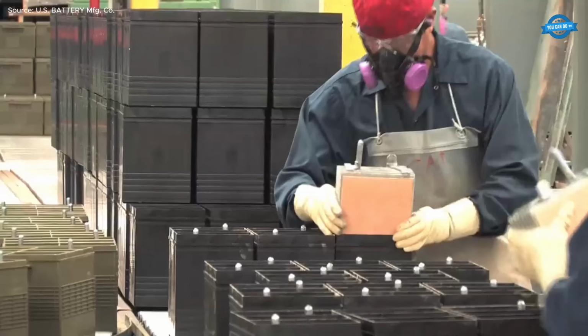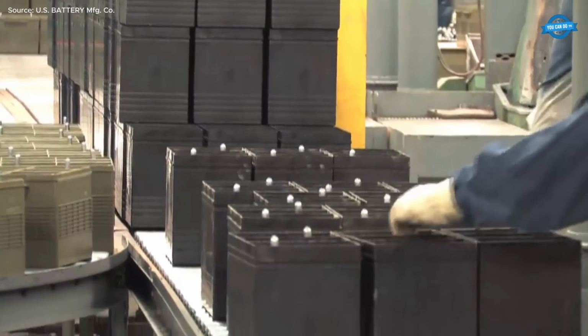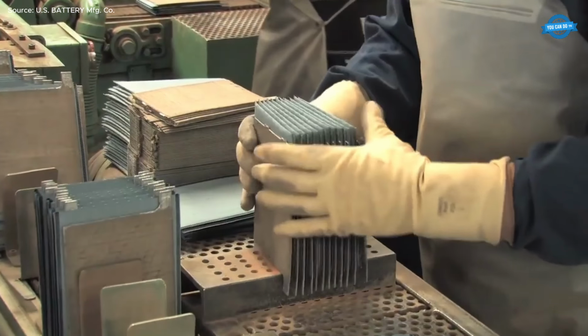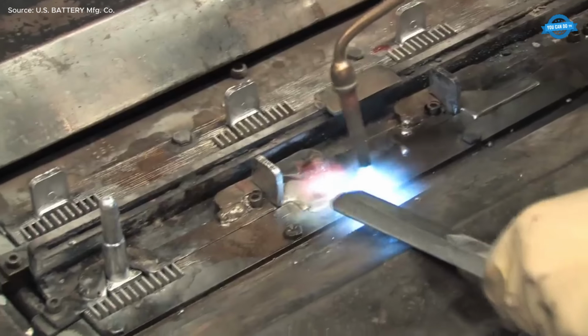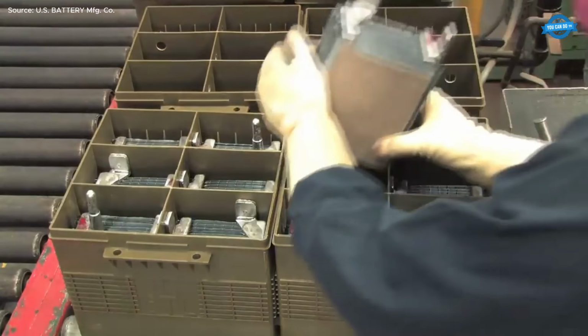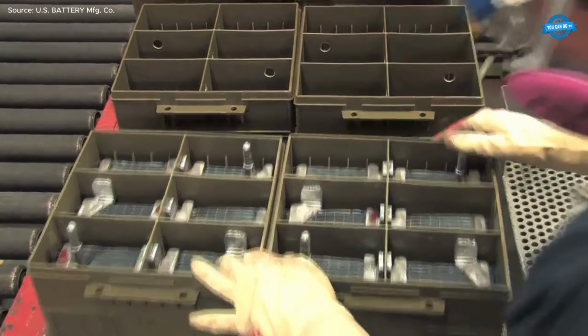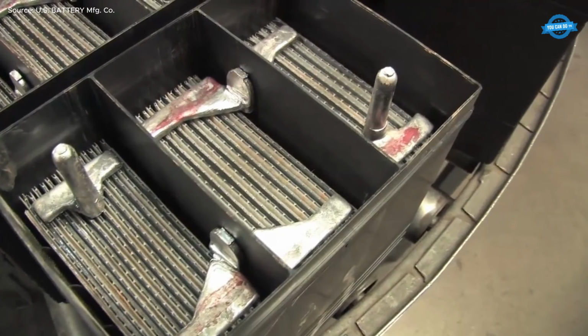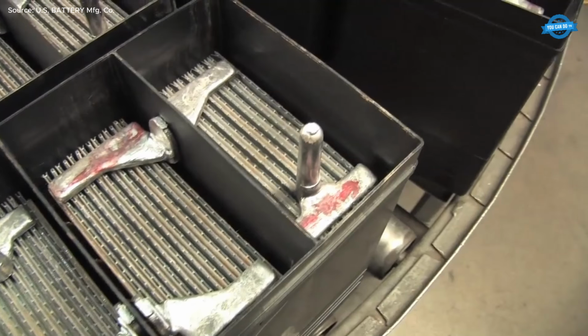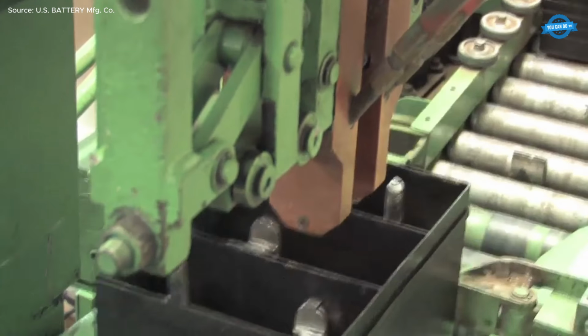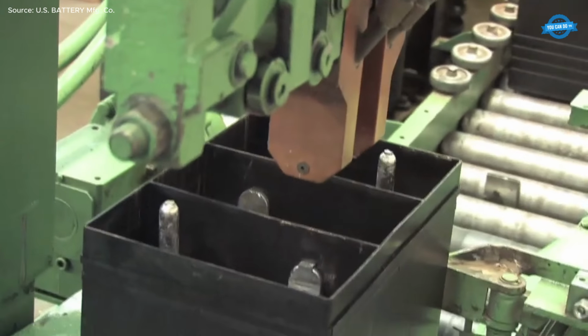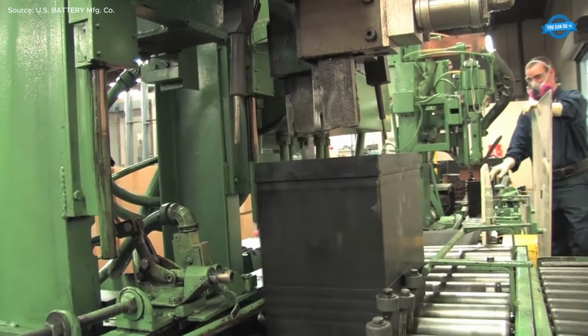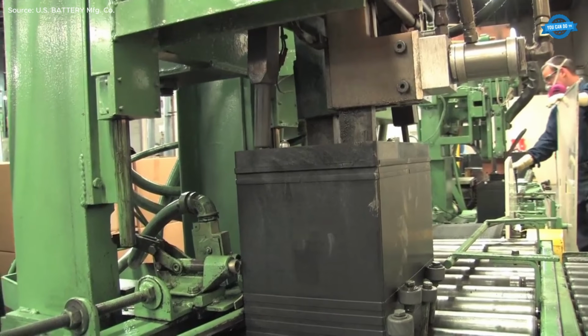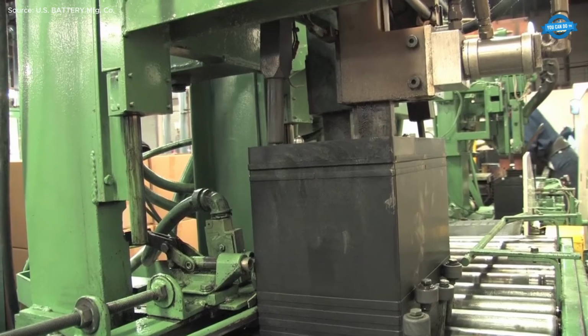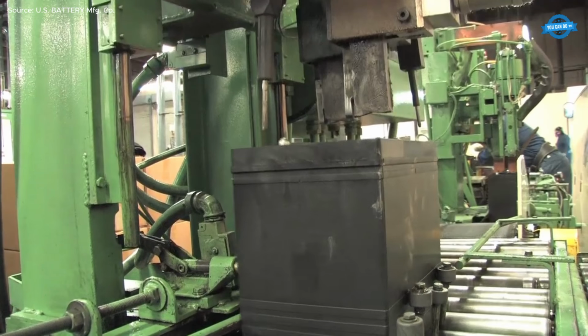A key differentiator is the company's proprietary XC2 diamond plate technology, which optimizes paste conductivity and increases active material utilization. Mixed oxide paste is applied precisely onto the grids and flash-dried before entering curing ovens. This produces stable crystal morphology, giving the plates higher capacity and extended life compared with conventional deep-cycle designs.